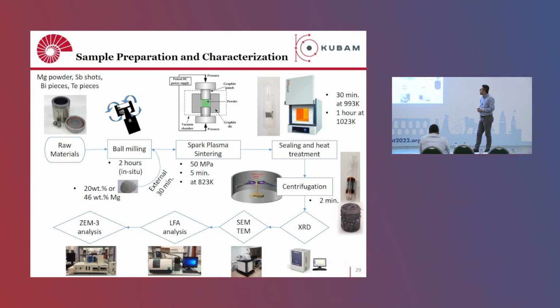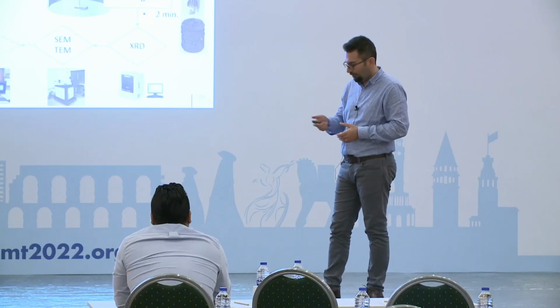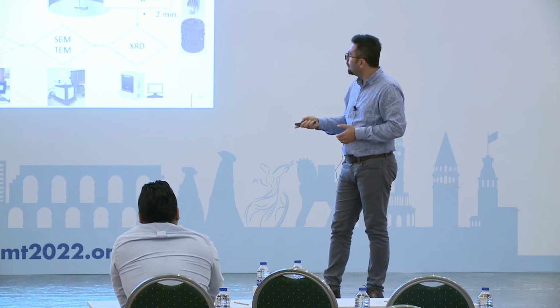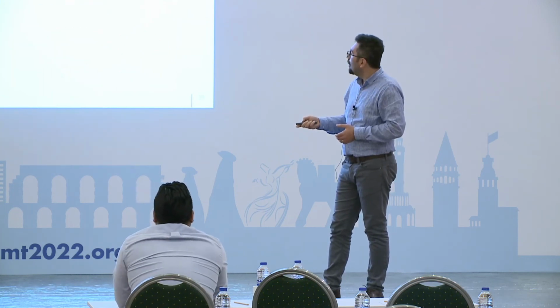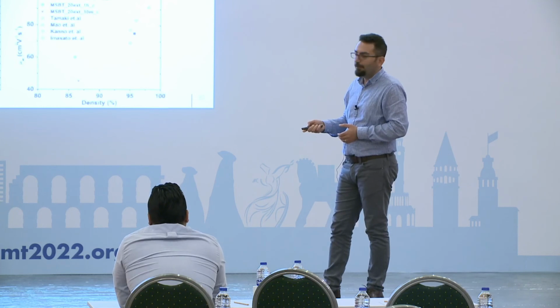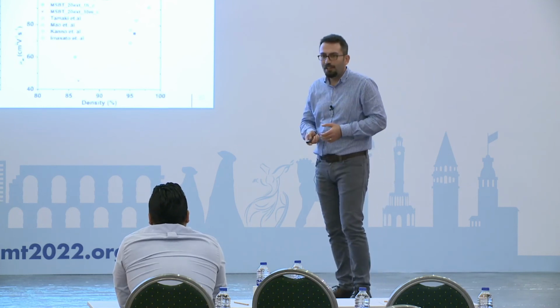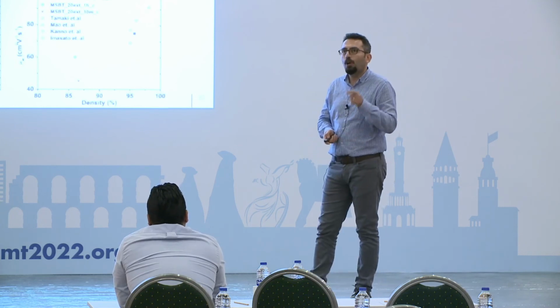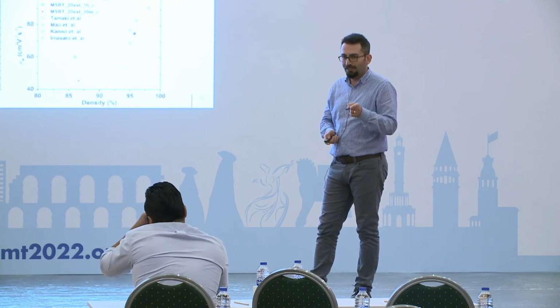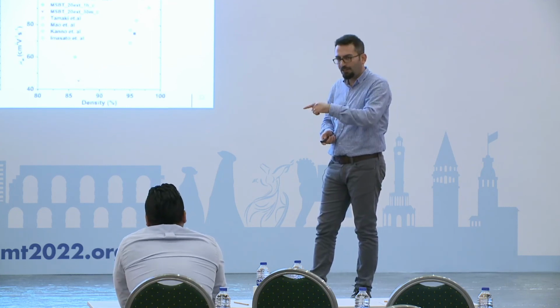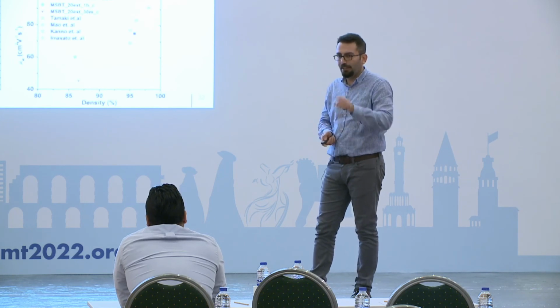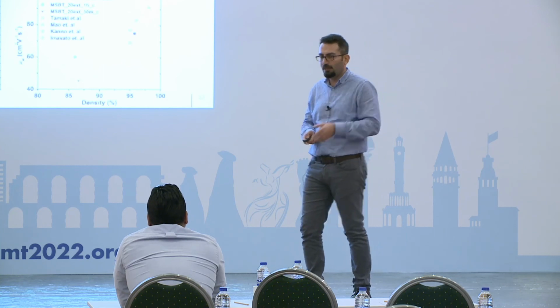Thank you. Maybe the last question I can ask you: the copper telluride has the same crystal structure as the antimony telluride, right? No, they are completely different. Copper telluride has, I think, an orthorhombic structure at low temperature, and it goes to a tetragonal structure, and then to a hexagonal structure. Copper tellurium two has a different structure from the antimony telluride.